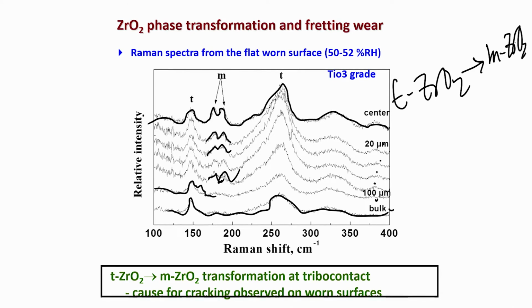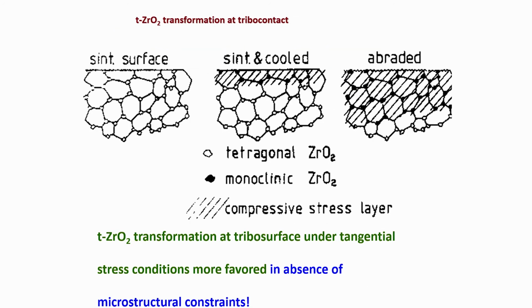Okay? And the phase transformation is not only associated with the volume increase, but also associated with the microcracking. Basically, crack tip strain energy is released by the formation and limited growth of the microcracking. Now, how do this microcracking and phase transformation take place? We are trying to explain this here with some similar reports from the literature, not exactly against the same counter body, not exactly under the same testing conditions, but we believe the mechanism may be similar.